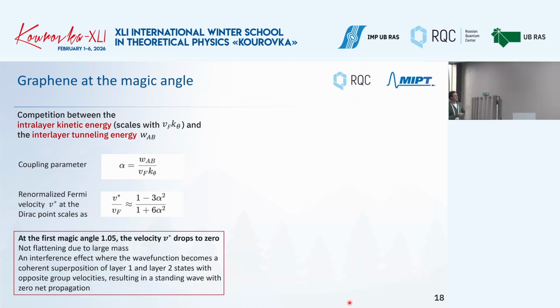Anyway, moving forward. It turns out that there is a competition between intralayer kinetic energy and interlayer tunneling energy, and there is a coupling parameter alpha that can be described like this. You can talk about the renormalized Fermi velocity at the Dirac point, and this all depends also on alpha. So you have the interplay between kinetic energy and tunneling energy. At the so-called first magic angle, around 1 degree, when you rotate one layer on top of another, this renormalized velocity drops to 0 in these areas.